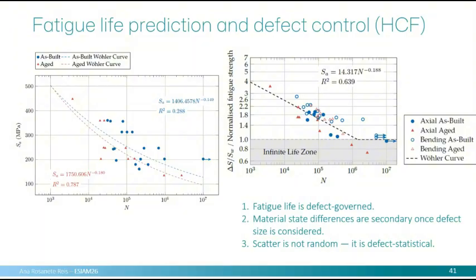Also the scattering again. But then when you go to the normalized results, you understand that we can normalize this, and then you have only the fatigue life governed by defect. So material state is not so important. But we understand that we cannot predict. So the defect, even if you minimize, if you reduce everything, is still quite statistical.